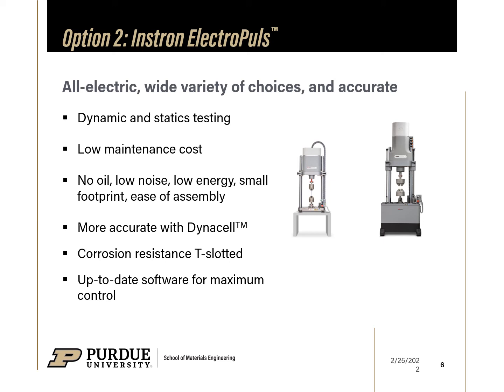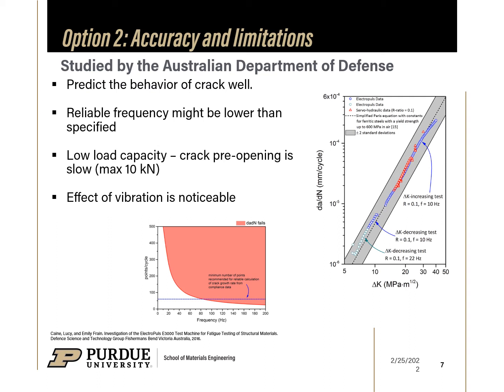It is more accurate now with a technology called DynaCell. DynaCell is a technology to reduce inertial errors due to fixtures and grips. It also includes self-aligning grips. It has a corrosion resistant T-slotted table. That means we can take any specimen for the testing without worrying about corrosion. And also it has up-to-date software for maximum control and customization. As studied by the Australian Department of Defence, ElectroPuls has a good prediction for the behavior of crack according to the graph. The blue dots follow the Paris law nicely and are aligned with the servo-hydraulic data.